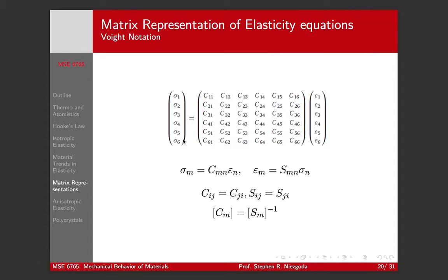Right? So we can write our transformation equations as, if A is a second order tensor, A prime, or transformed A, equals Q A Q transpose. I have a matrix way of writing that transformation. That's not true for fourth order tensors. So I can write a matrix that represents a fourth order tensor, but that matrix does not transform. We have to always think about transformation relationships with respect to the full fourth order